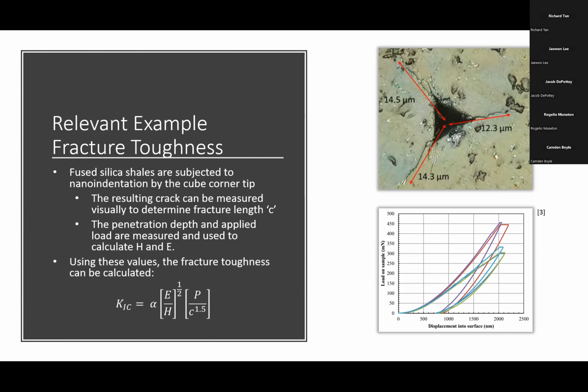Using optical imagery, you can measure the distance of each of those fracture patterns, labeled C. The penetration depth and applied load are measured as usual and used to calculate the hardness and Young's modulus. Using all these collected values, you can calculate the fracture toughness using the equation shown at the bottom.